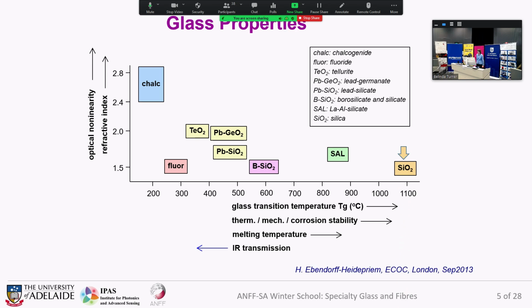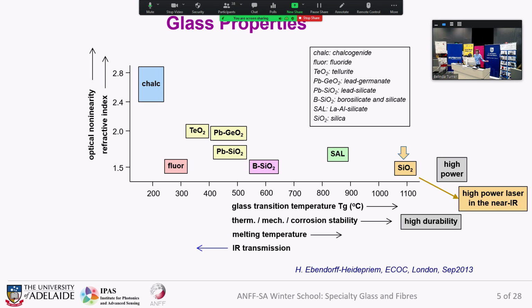First, silica on the right side. So it has the highest glass transition temperature, therefore you can imagine it is the glass with the highest durability. On the other side, it has a low refractive index. What this means is one can transport high power without running into nonlinear effects. And so therefore, silica is perfectly suited for high power laser applications in the near infrared.